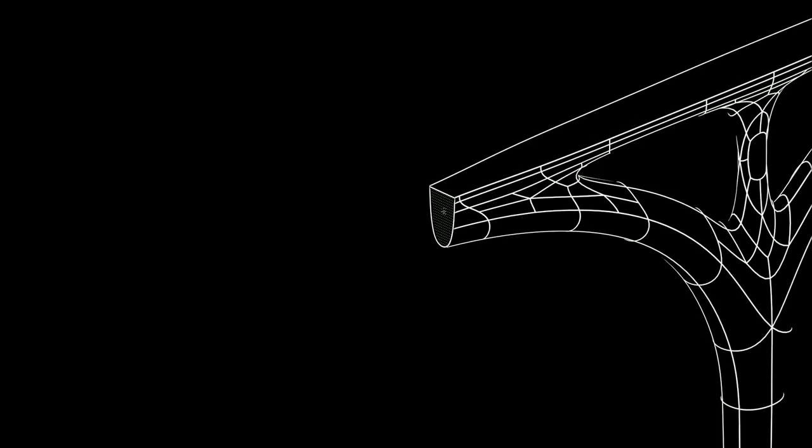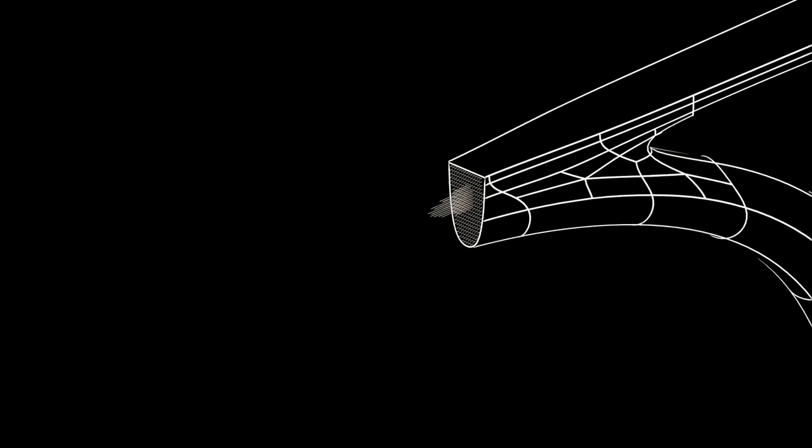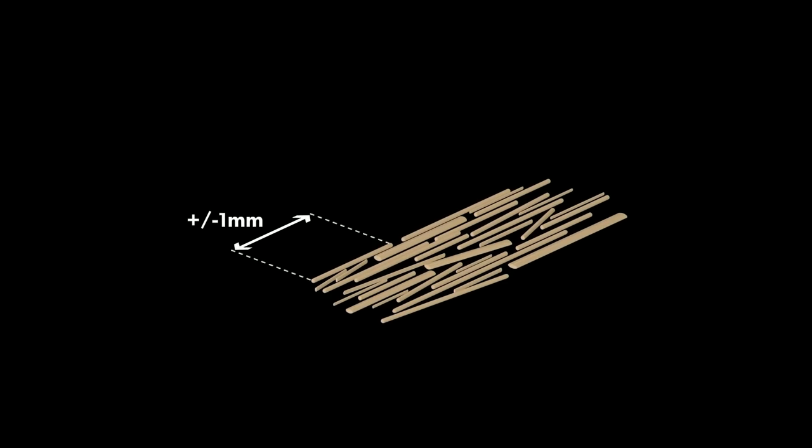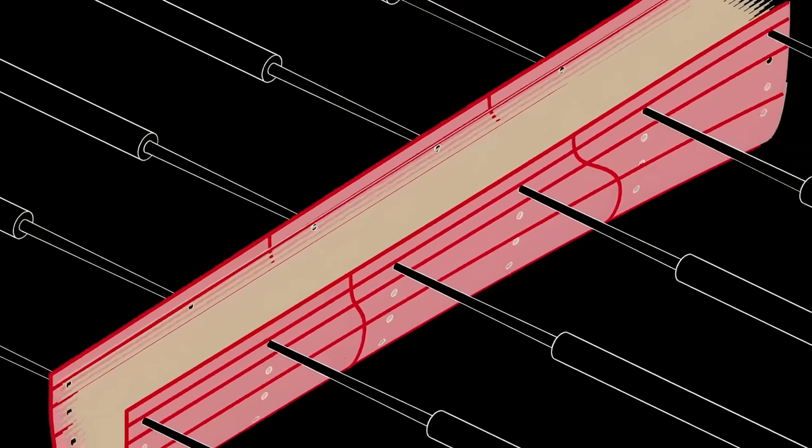As we zoom in even further, we start to see how it's actually composed. And you may think in your mind, is this fiber board, is this particle board, things you've seen before? Well, actually, what we're talking about is a very microscopic layering of these plant fibers. They're just a millimeter long. By laying them together and cross-laminating them across each other, we can customize the way, based again on the structural model, exactly how the composition of each piece of the material works in order to make it as efficient as possible. We combine it with these organic polymers and lignin, and ultimately make this material as strong, dense, and behaves much like a tree.